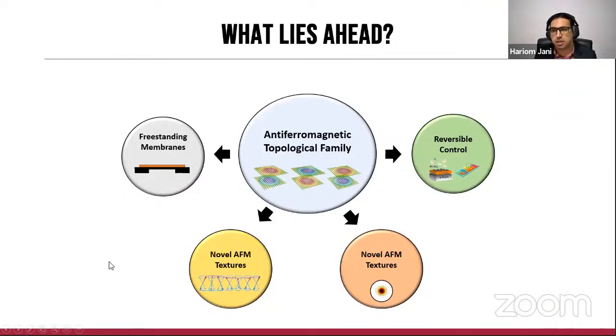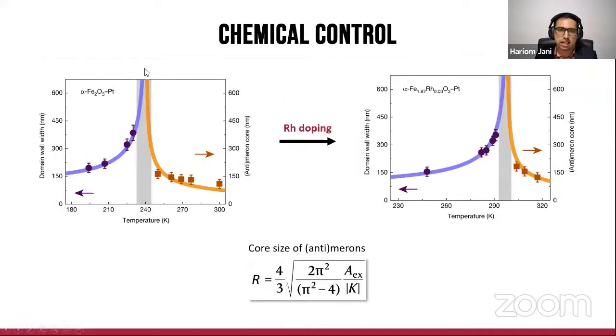Lastly, I would like to discuss a possibility of controlling the magnetic topological family by reversible control processes, given the fact that Fe2O3 actually hosts rich correlations between various orders. So first and foremost, I would like to go back to the chemical doping aspect, where we used rhodium doping to completely shift the transition. While this was exciting, this is a slightly limiting process because it is an irreversible transition. Once you make a certain amount of rhodium doped Fe2O3, it is going to remain in that state.